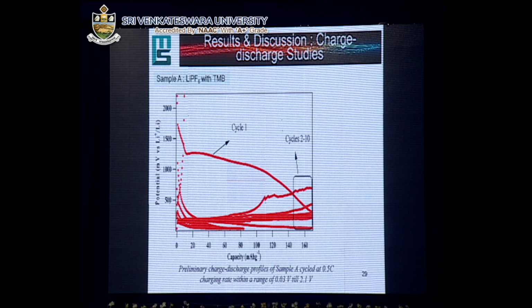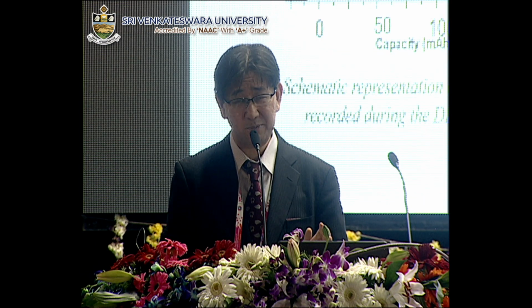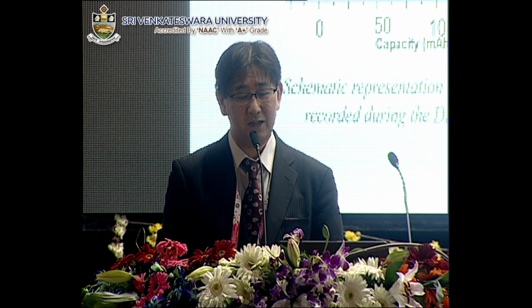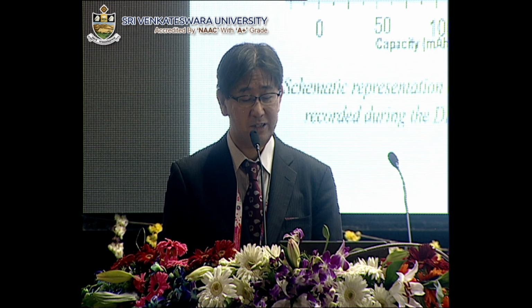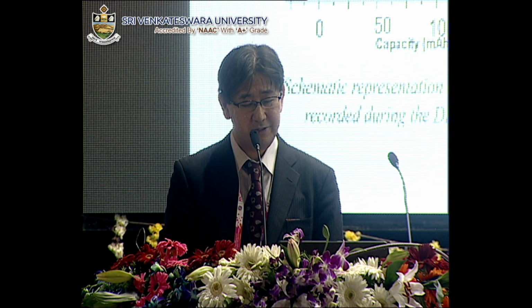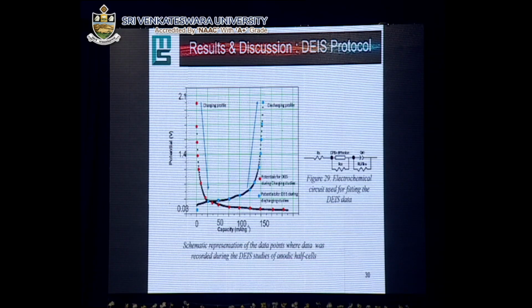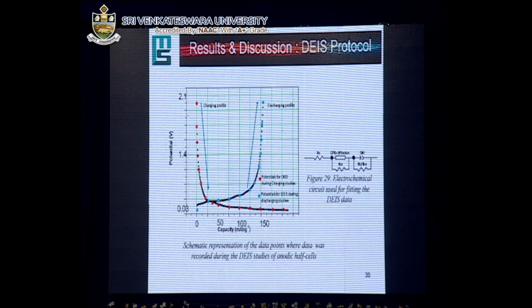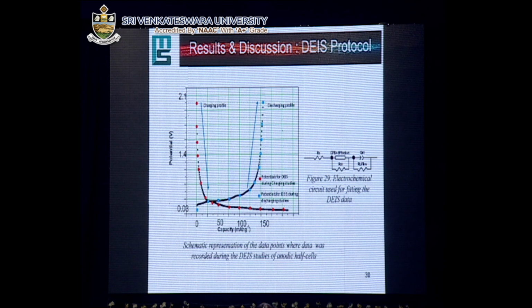But in the initial attempt, no successful charge discharge was observed. So we tried to optimize the charge discharge conditions utilizing the dynamic electrochemical impedance spectroscopy (DEIS) technique. And here, DEIS is not a mere in situ impedance measurement during the charge and discharge, but at each point of in situ impedance measurement, an external DC potential was superimposed on the battery cell to enable the same state of charge as actual battery cells.